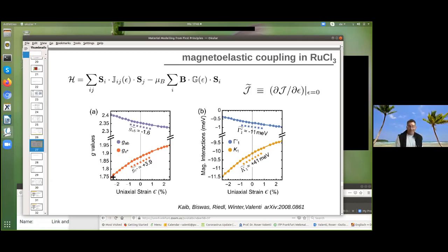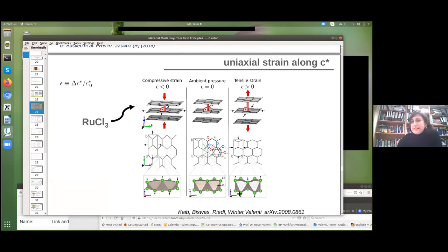Yeah, I guess it answered half of my questions because I also took this picture as the decrease of both K and gamma prime. Yeah, sorry. So the left plot shows that the G factors become more, am I reading it wrong again? They're becoming more free electron-like. So here, the G factor, when you go into this tensile strain, basically you are sort of doing a compression in ruthenium trichloride, and what you're getting is more symmetric octahedra. And that's why your G factor gets less anisotropic.